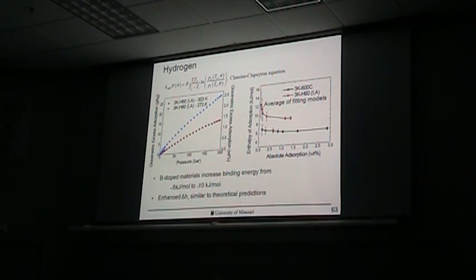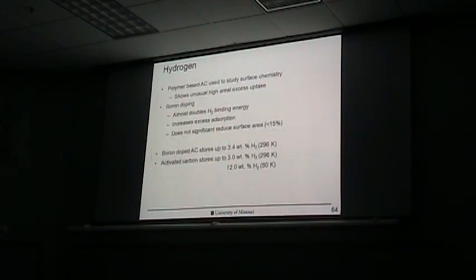We can calculate the binding energy by measuring 2 different isotherms at different temperatures. With the so-called Clausius-Clapeyron equation, you can calculate how much the binding energy is. You see it over here. This is the binding energy without doping, and this is with doping. You can see we almost doubled it with the boron doping. So at the end, the activated carbon made from PVDC shows a very high areal excess uptake, so it absorbs a lot of gas per surface area, which is unusually high. With the boron doping, we can almost double the binding energy between hydrogen and the surface, and we don't lose a lot of surface area.